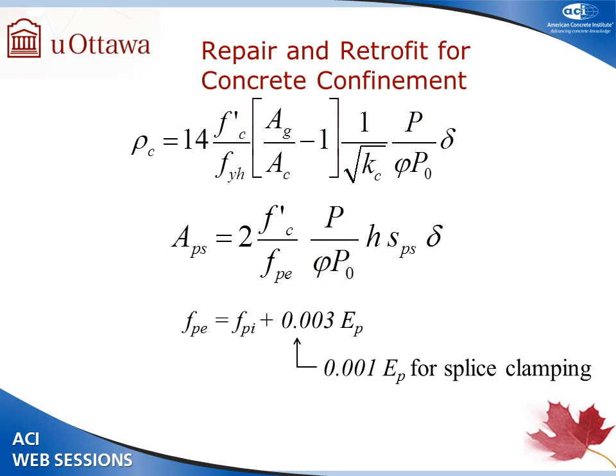For retrofitting for confinement, we were able to use the expression that was developed earlier, which is a function of lateral drift, axial load, and cover to core area ratio. In this case, there is no cover to core area ratio because it's applied externally, and hence we substituted the minimum value of 0.3 in that bracket and obtained this area of prestressing.